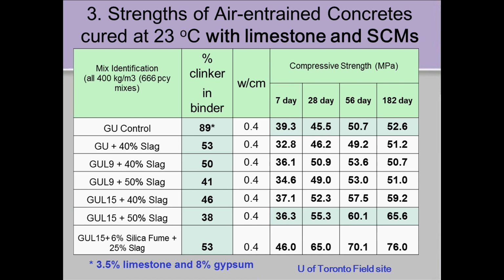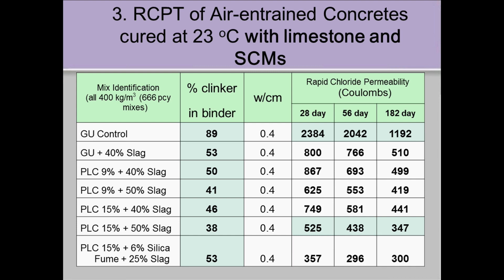And we've done this in other studies. We're doing a lot of work on sulfate resistance. And just to highlight the top row, if you just took a plain Portland cement concrete, these are 0.4 water-cement ratio concretes. These are strengths from 7 days through half a year, with about 90% clinker content in that cement. But if you go down to the other one I've highlighted, with 15% limestone in the cement and 40% or 50% slag, we're only using 38% clinker in that concrete. So we've reduced the CO2 burden on the concrete by about half. And again, we've got equivalent strengths, maybe slightly less, 500 psi less at 7 days, but higher strengths at later ages, and so with big reductions in the CO2. And if you go to the permeability, huge differences versus Portland cement if you use the limestone and the slag.